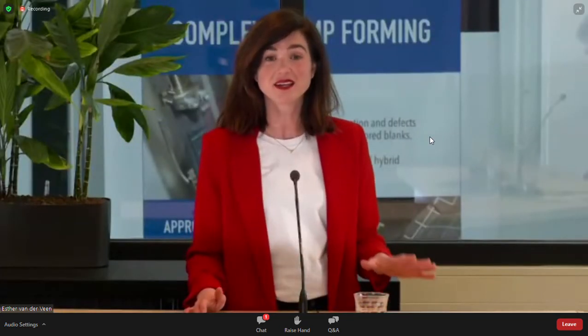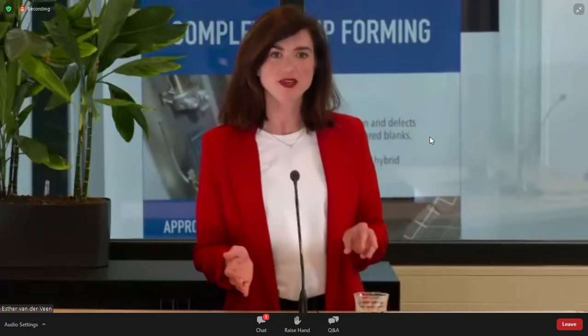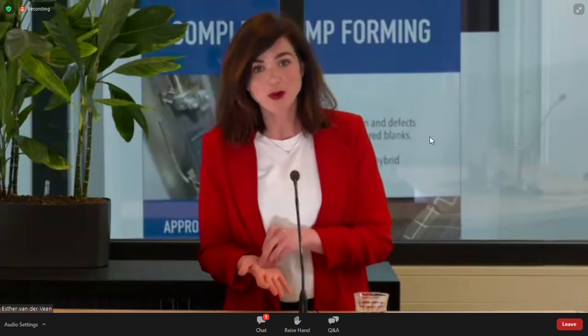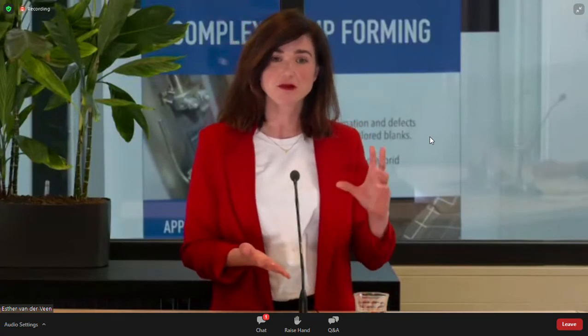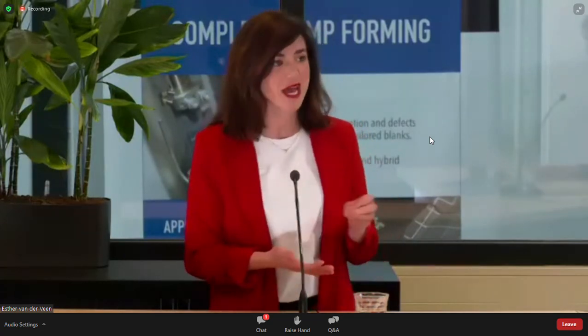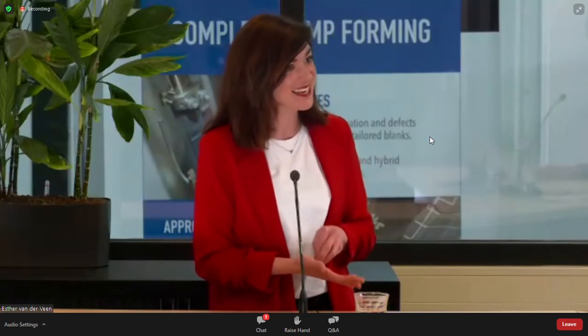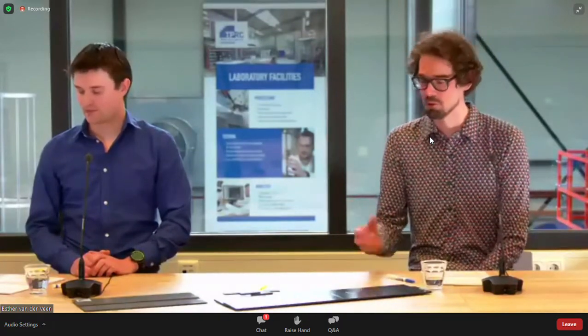Yes, like Yannick is pointing out in this video, we want the heat exactly at the right spot. And with induction welding, we create current within the material. But how do we get that heat exactly at the interface? That's one of the main challenges, and physically this is not really possible. So we will always generate heat in our materials, whatever you do, unless we use an energy director or we change the materials we want to weld. And this is not something we would like to do.